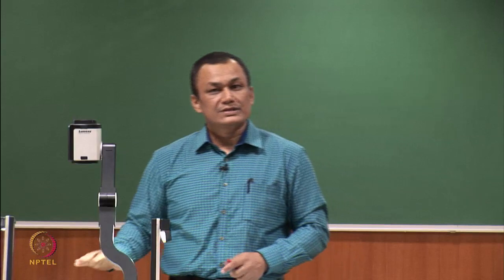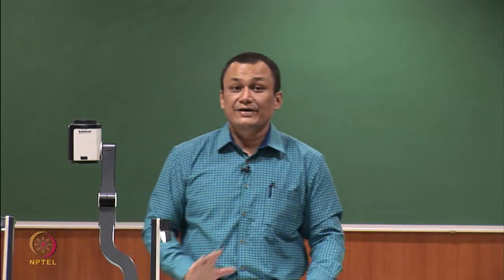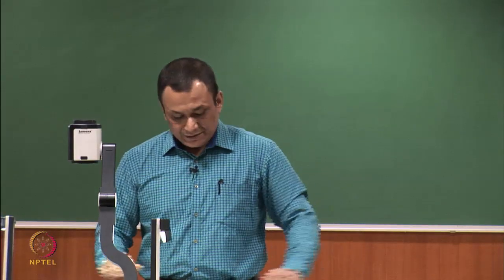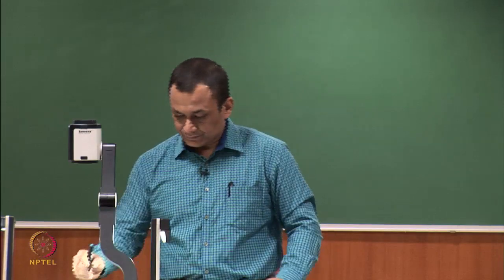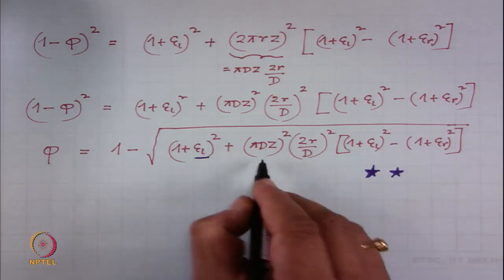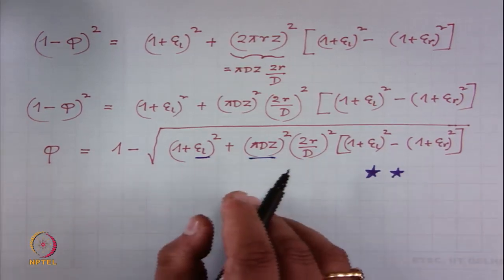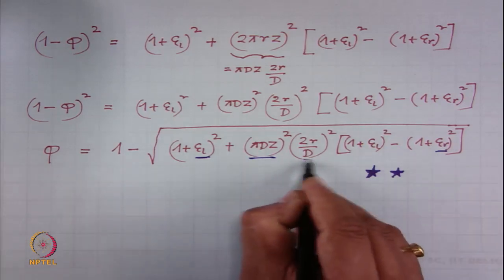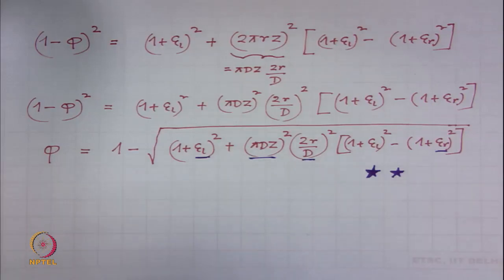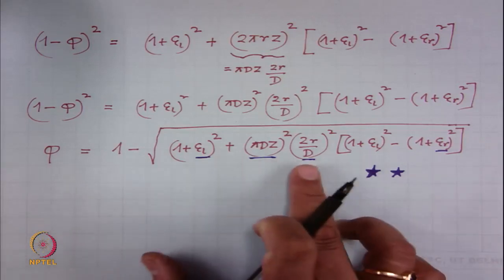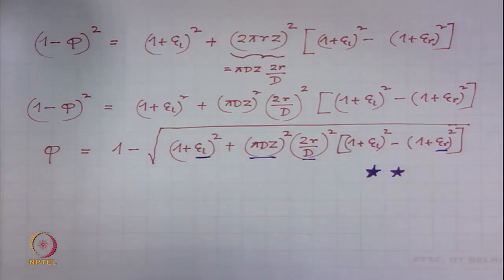Now, what this equation tells to us? It tells us a very interesting story. These parameters epsilon L, twist intensity kappa, epsilon r, this diameter d, they are constant for a given yarn. So, for a given yarn, epsilon L, kappa, capital D, epsilon r are constant.